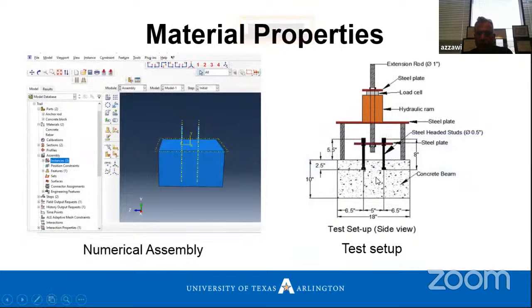So we did the modeling in Abaqus here, and this is the numerical assembly. The embedded anchor bolt, as we see here, we modeled inside the concrete unit. We use displacement control to apply the load. In Abaqus, this is the test setup. As we see, we have 2 anchor bolts tested at the same time, and we have all these test instruments. We try to match them with the modeling, especially the boundary conditions.